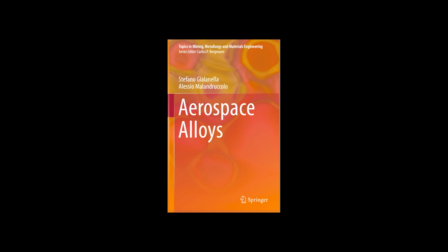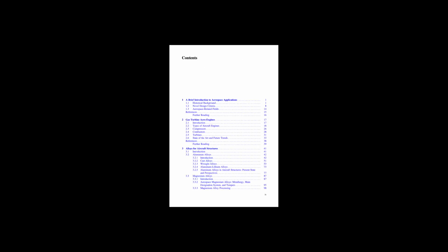And single crystal is the next step. It's the ultimate step in that direction. Single crystal, or SC, casting uses a special pigtail or spiral structure in the mold base that acts as a grain selector. As solidification starts, multiple grains form, but only one is oriented correctly to grow up through the selector and form the entire component. Sometimes they use a seed crystal. Yes, they can place a small seed crystal with the desired orientation at the bottom to ensure the final part has that specific crystal alignment relative to the blade's geometry. By completely eliminating grain boundaries, SC casting provides the absolute best creep resistance.